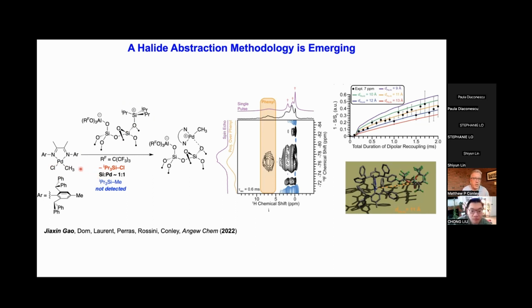We also see that we have 1 palladium on the support per triisopropylsilyl chloride evolved by correlating the amount of TIPS chloride that comes off in solution and the amount of palladium by ICP analysis.